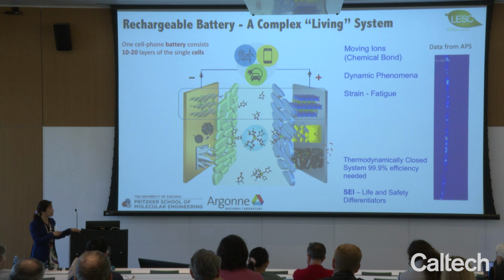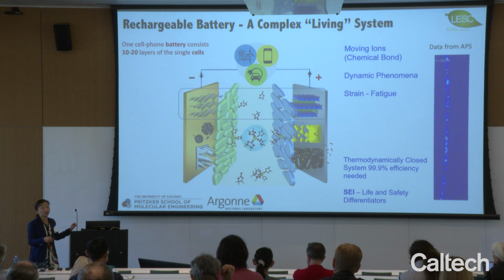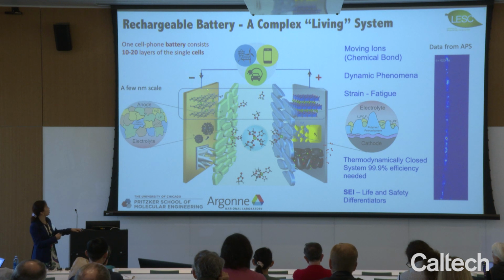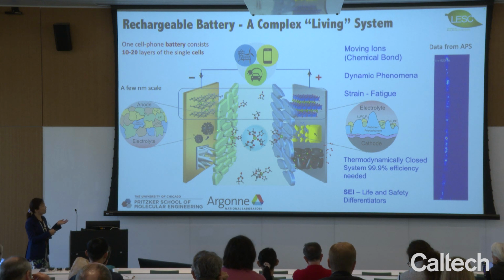And all of these have to be done with the restriction that we are in a thermodynamically closed system. So the Coulombic efficiency has to be extremely high, because every side reaction causes you loss of energy carrier, which is either lithium or sodium ions. So this becomes so challenging, and the weakest link in the cell is always at the interface between the electrode and the electrolyte.